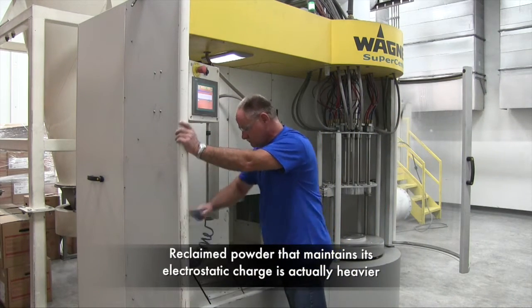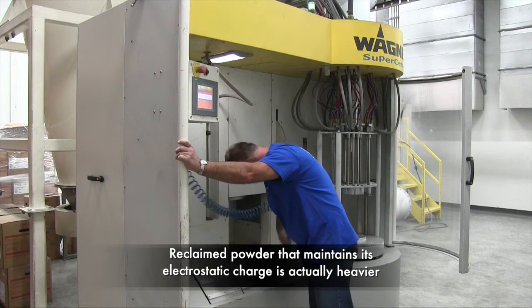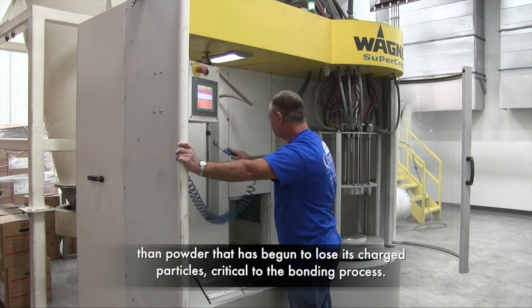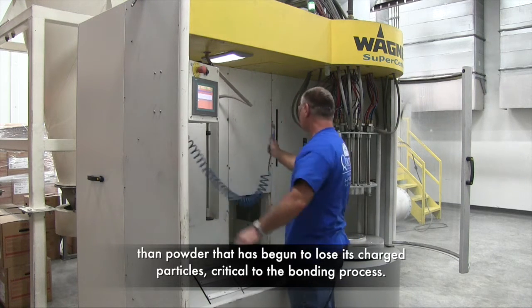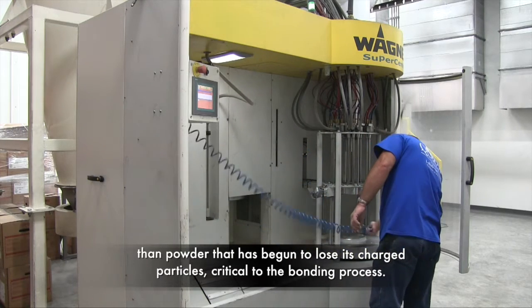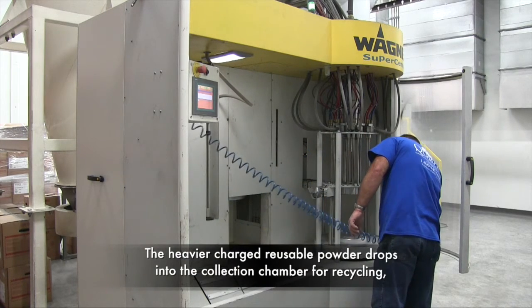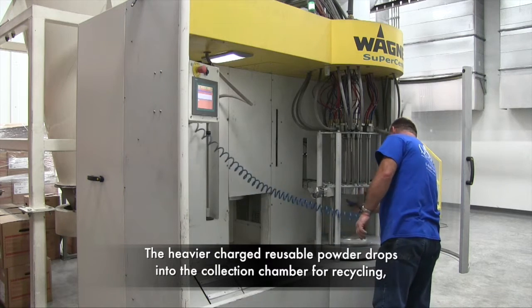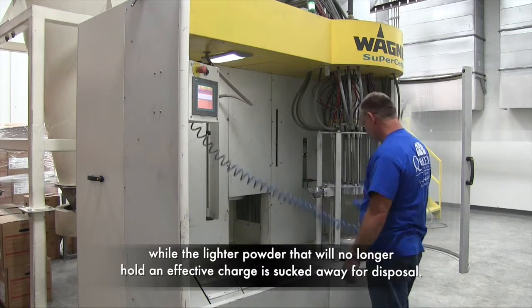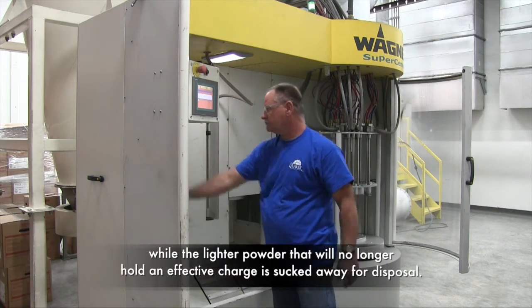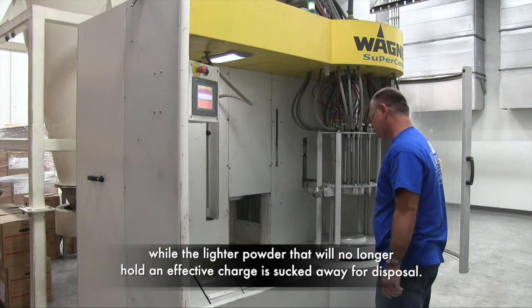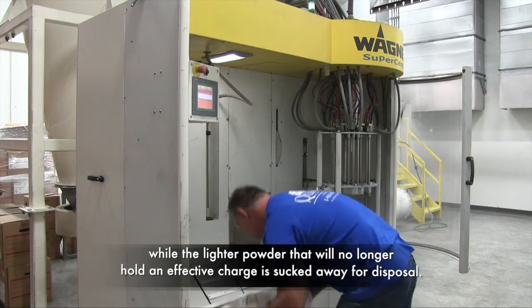Reclaimed powder that maintains its electrostatic charge is actually heavier than powder that has begun to lose its charged particles critical to the bonding process. The heavier charged reusable powder drops into the collection chamber for recycling, while the lighter powder that will no longer hold an effective charge is then sucked away for disposal.